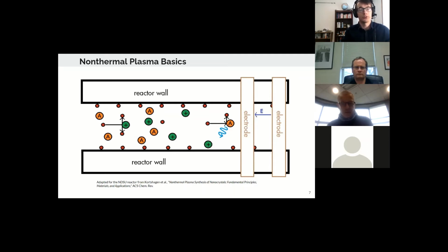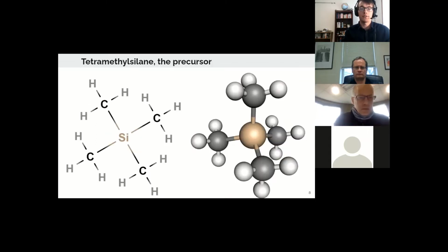plasmas as well, with pressures in the tens of torr. Our NDSU reactor is optimized for use with liquid precursors. So the precursor chosen was a liquid. An ideal precursor would have low toxicity to humans and would be non-pyrophoric. And the organosilicon compound tetramethylsilane fits these requirements well. I'll refer to tetramethylsilane interchangeably with its abbreviation TMS.